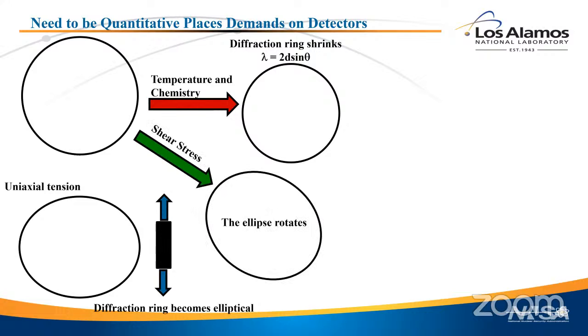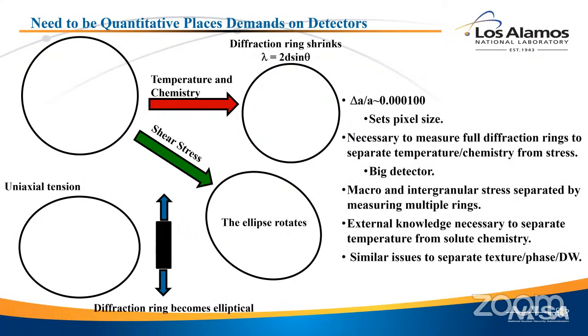Now, a shear stress actually is a little different, where a uniaxial stress turns it into an ellipse. The shear stress rotates that ellipse. Okay, it rotates the major and minor axes. So again, those are things that I can separate out. So these are all the things that go into when I make a measure of lattice parameter. I consider all these things when I interpret it from lattice parameter, which is not very useful, to internal stress, which is something that's useful. And that's the case for all microstructure features that we're going to pull out. There's everything I just said written down.